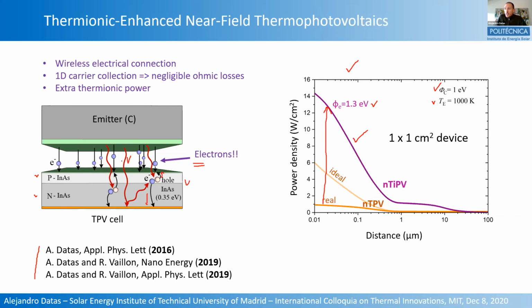So the idea is that with this concept, you avoid any electrodes in the probe. So there is a wireless electrical connection between the emitter and the photovoltaic cell. There is 1D carrier collection, and this is really, really important because 1D carrier collection avoids the lateral conduction of minority carriers in the photovoltaic cell, and then it enables negligible ohmic losses. And of course, you also have an extra thermionic power, which is basically due to the voltage that is established between the emitter and the front side of the cell. So then you get this much higher power density.